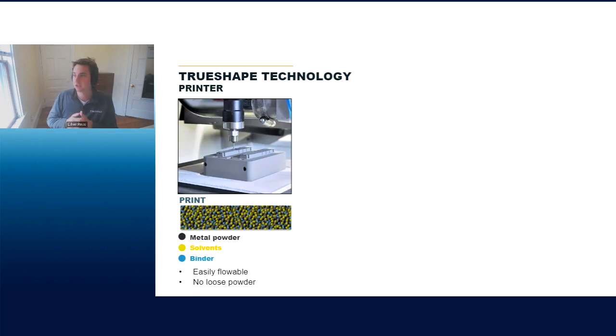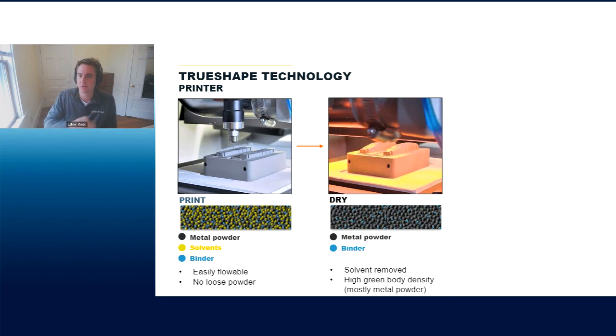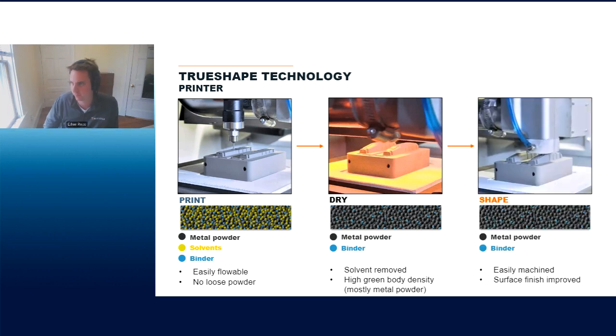So we start by simply printing a layer of this paste. We're just extruding it out of a needle like you're seeing here on the left. The solvent makes the material viscous enough that it can simply flow. It can easily be extruded into the place that you want it. After each layer is printed, we go through and dry that layer. So what's happening here is that the solvent is actually being removed out of the layer, leaving behind just metal powder and binder. And lastly, one of the most important steps here is the actual machining step.